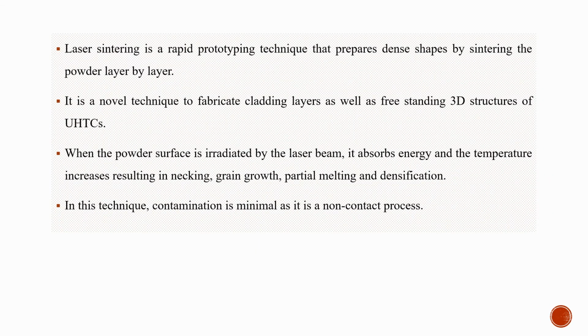Laser sintering is a rapid prototyping technique that prepares dense shapes by sintering the powder layer by layer. It is a novel technique to fabricate cladding layers as well as freestanding 3D structures of UHTCs. When the powder surface is irradiated by the laser beam, it absorbs energy and the temperature increases, resulting in necking, grain growth, partial melting, and densification. In this technique, contamination is minimal as it is a non-contact process.